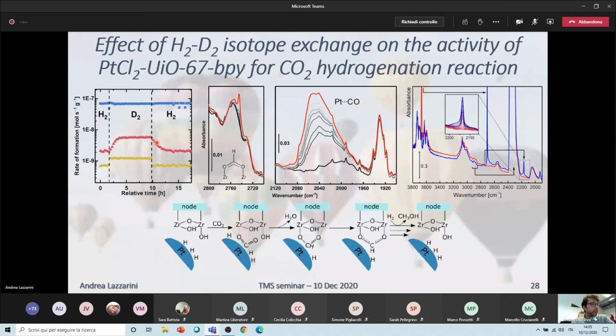And what we ended up with was that these formate species that are forming at the node and the platinum nanoparticle interface are the ones that are responsible for the formation of methanol.